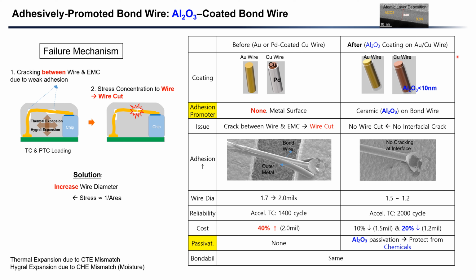On your right-hand side, if we introduce aluminum oxide coating on the surface of the conventional bond wire, you can increase the adhesion so we don't have interfacial cracking between a bond wire and an EMC, so we don't get a wire cut failure.